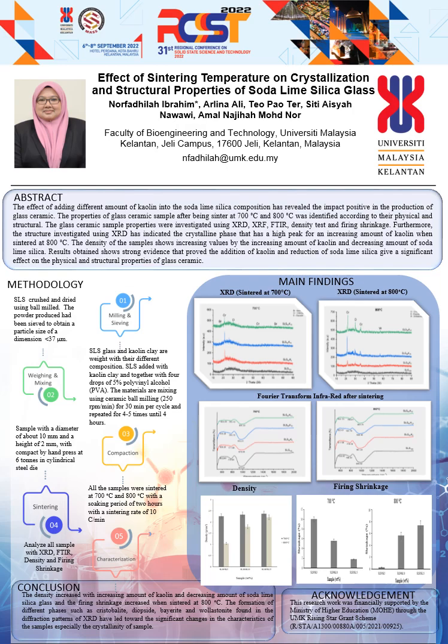Meanwhile, for firing shrinkage, that's different. At 700 degrees C, the shrinkage decreased. Meanwhile, for 800, the firing shrinkage increased. So it's a contrast between the two of them.